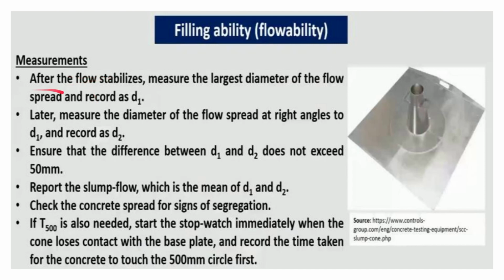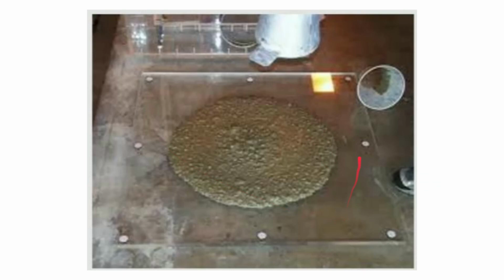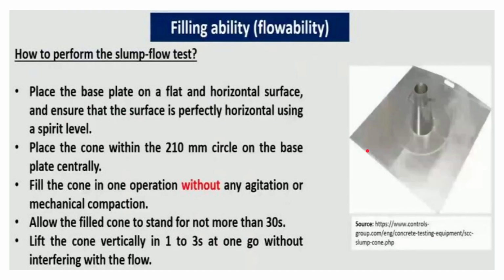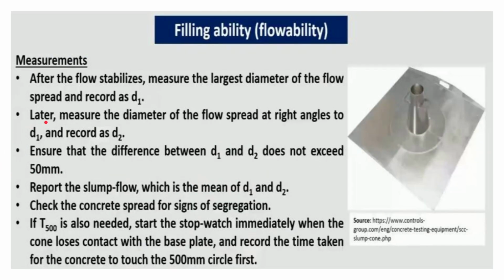Okay, so after the flow stabilizes, we measure the largest diameter of the flow spread and record it as D1. As you saw here, we find the direction where the largest flow occurs, say for example this direction, and we measure this flow spread. So this is basically the D1 value, the largest diameter value.